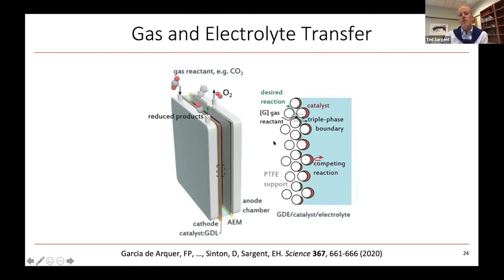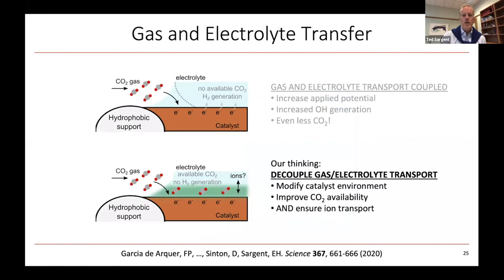But it turns out that even when we get into this triple phase boundary business where we've got our gas reactants coming in from the gas phase, we've got our catalysts shown in brown, and then the optimal activity is right at this triple phase boundary, it still turns out that we do have some challenges left over, and I'm going to illustrate those here. So if we're sitting on a hydrophobic support shown by the gray, and then there's some effectively meniscus with the aqueous electrolyte shown here. Right where the CO2 comes in from the gas phase, meets the aqueous solution, and then sees catalyst, we're in good shape.